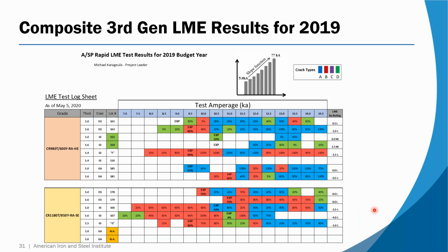Okay, I think that addresses the second question, which the commenter indicated that some studies have shown that GA coatings show a lot less LME susceptibility compared to GI. I think you've basically stated that we have inconclusive data. Not enough testing was done for us to be able to determine that. Would you concur? Right. If you looked at these two green GIs, and that's all the data that you had of GI, and you compared that to GA, you'd say the opposite would be true. I'd rather have GI than GA. But if all you had to compare was material F versus the GA, you'd say, oh, I want GA definitely. And you don't have enough data to really make a conclusion like that. But that's up to others to say. It probably needs to be a steel maker to study that, to know that the substrate is the same. You just changed the coating.